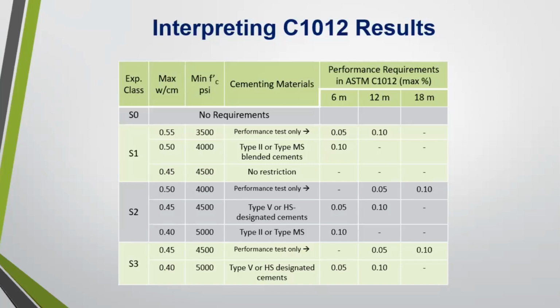There's really no special recommendations that are made. As you move down the chart, you will see obviously water cement ratio lowering, strengths a little bit higher, different cementing materials used. Let's move all the way down to an S3 designation for just a minute. So here we've got two options. At a 0.45 water cement ratio and 4,500 PSI, basically the only acceptance criteria is performance. So in this case, we would need, from C1012, results of less than 0.05% expansion at 12 months and 0.1% expansion at 18 months.